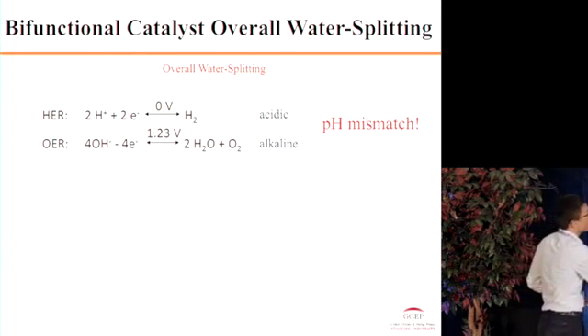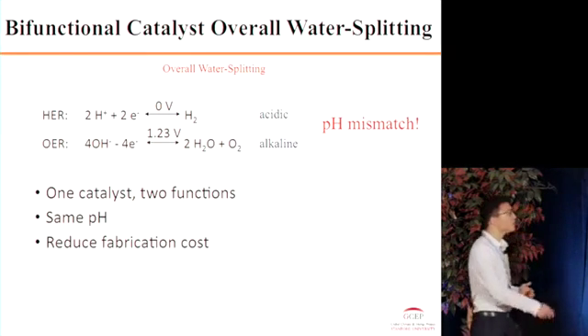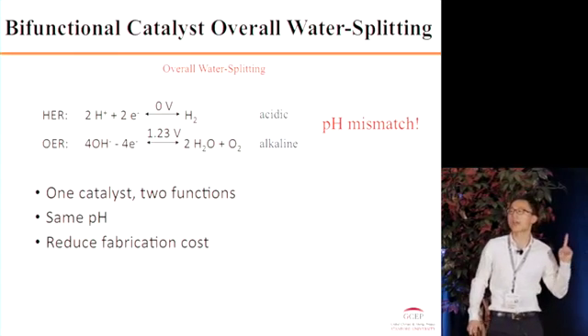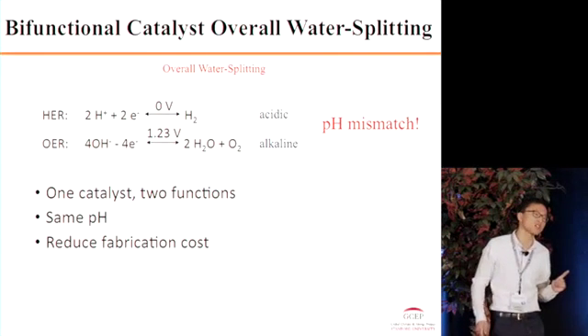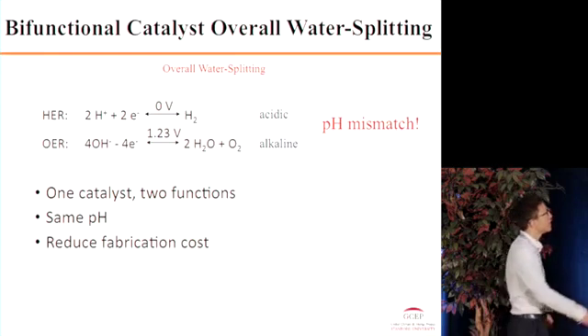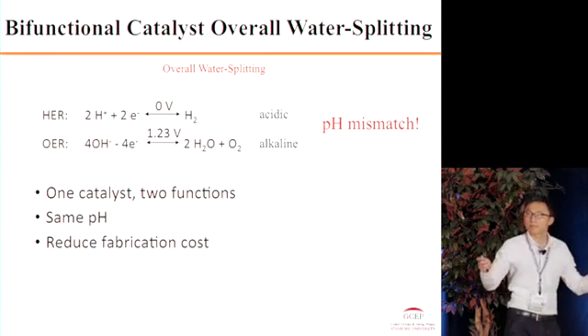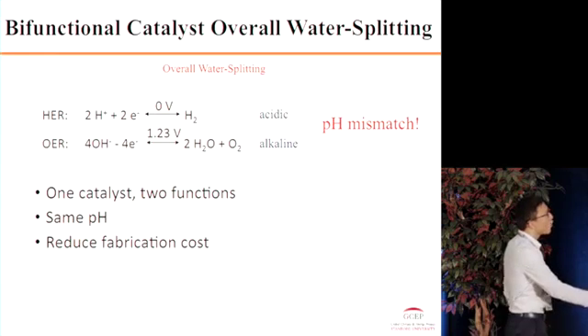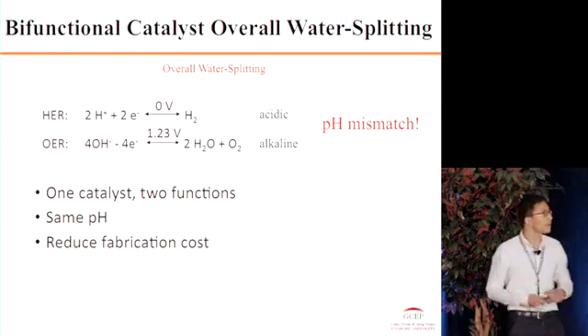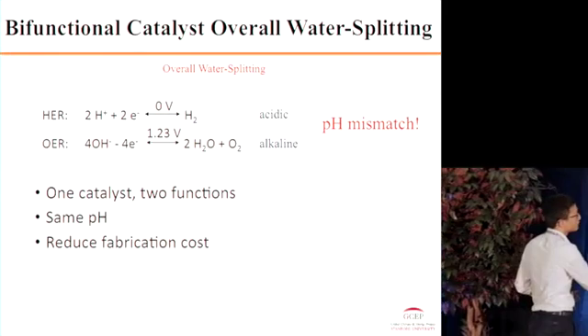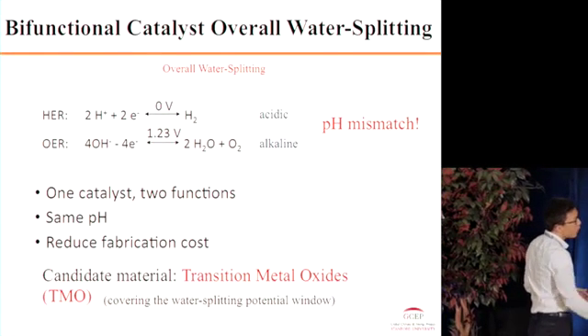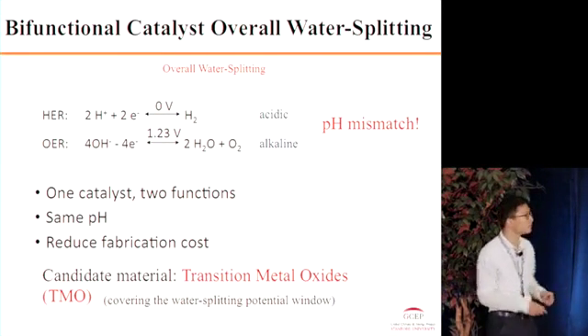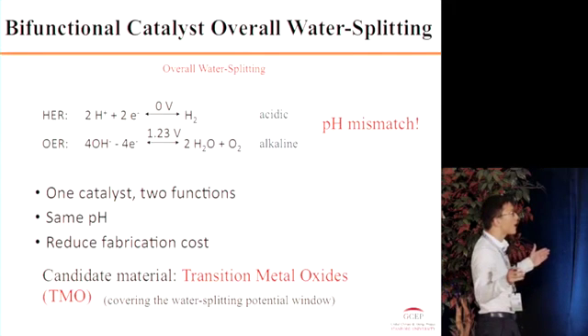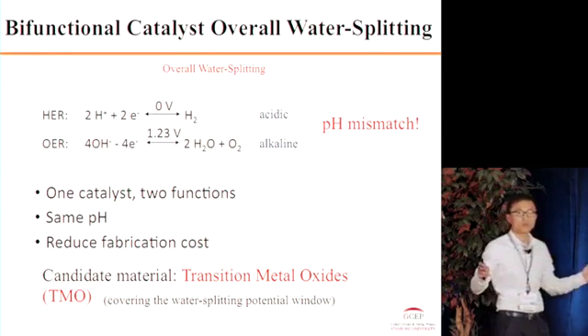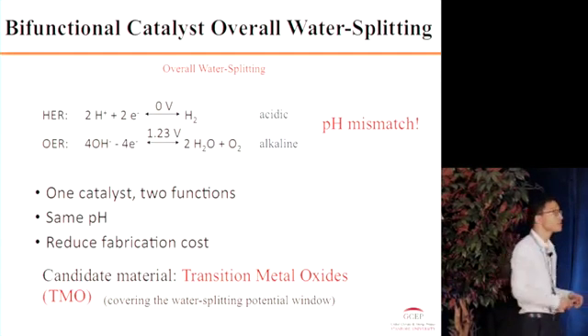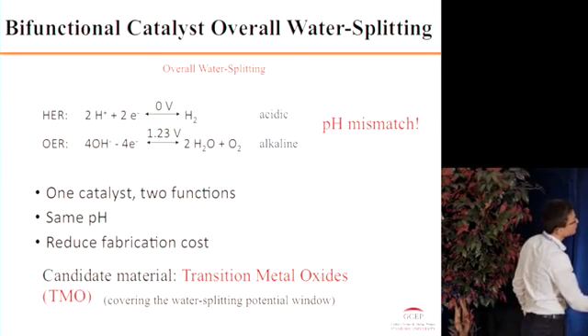how can we combine these two catalysts together in a real device? So the best way I can think of is to develop only one single catalyst that can drive both reactions, which we call a bifunctional catalyst. Then we can stabilize it in the same pH, so there is no pH mismatch. And at the same time, I reduce half of the fabrication cost of the system. And the candidate I want to choose is transition metal oxide. That has a very wide stable electrochemical window covering the whole water splitting potential window.